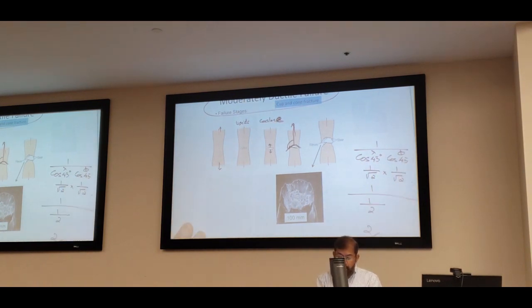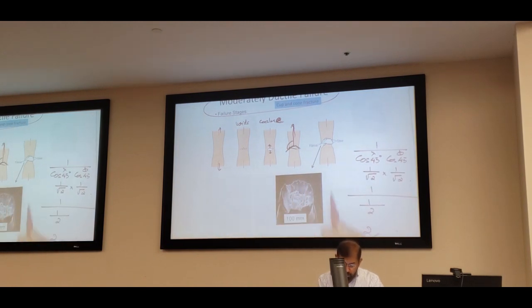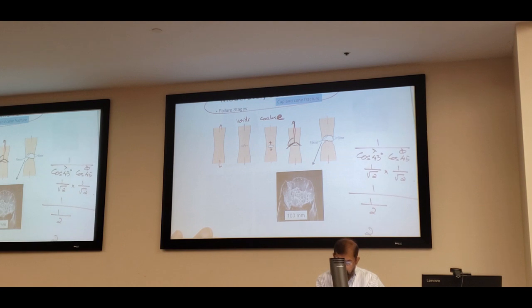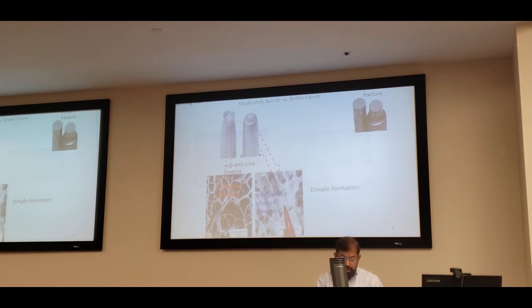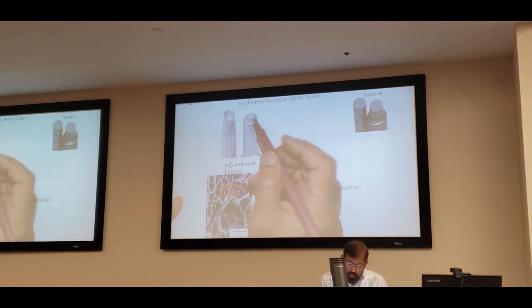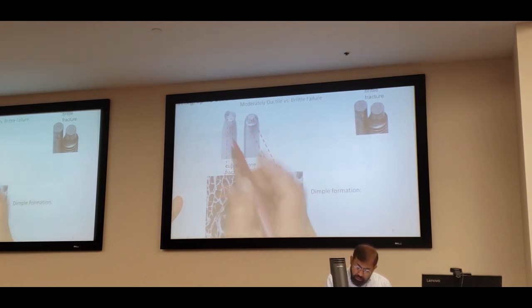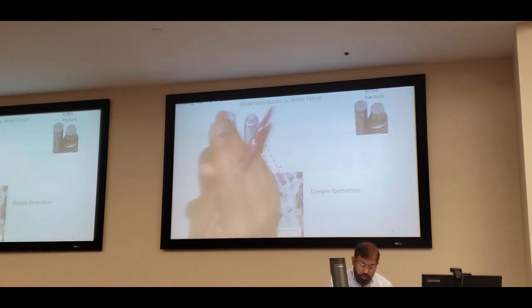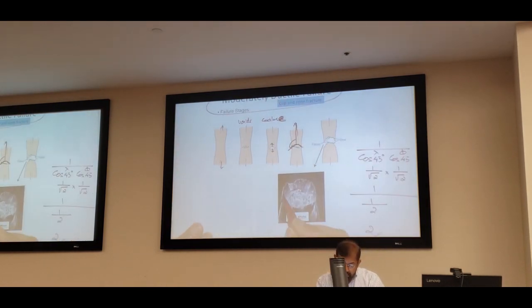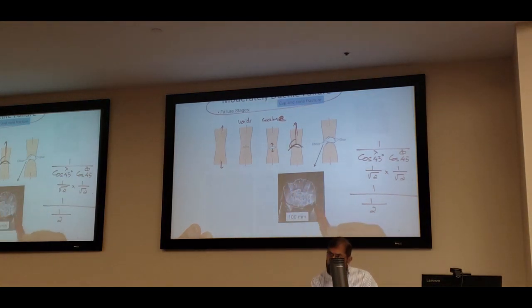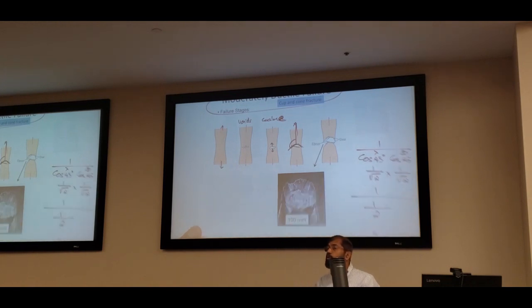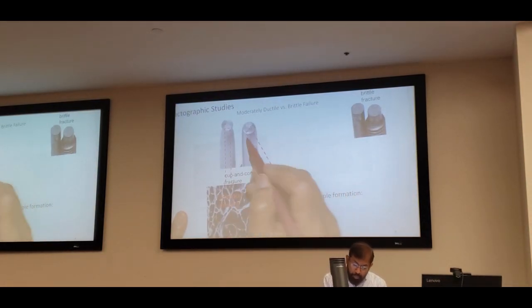It's a moderately ductile failure here, and this is an actual cross-sectional area of your sample. You can see that this lip is 45 degrees, and you can see more grainy structure on the surface, and that is the reason why you have a moderately ductile failure. So you can see this is called a cup and cone fracture. Look at this one. This part is a cup, and there is a cone. Since this is a cup, the other side should be a cone, and that's the reason why it is called a cup and cone structure.